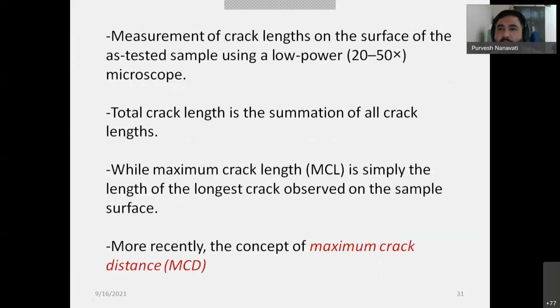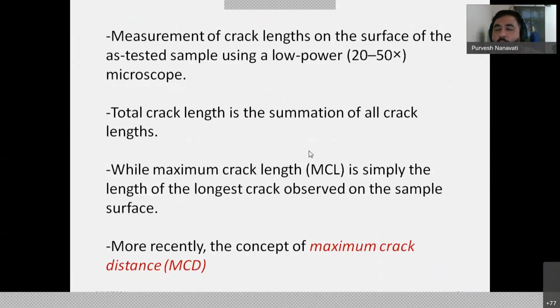So now, measurement of crack lengths on the surface of the as-tested sample using a low power microscope. Now, how would you examine the crack? You would examine the crack using a low magnification microscope, right? With a 20 to 50x microscope. And the total crack length is the summation of all crack lengths. Now, there are various concepts like TCL, total crack length, like MCL, maximum crack length. And the most recent concept is the maximum crack distance, that is MCD. Now, most of the people measure MCD, maximum crack distance.